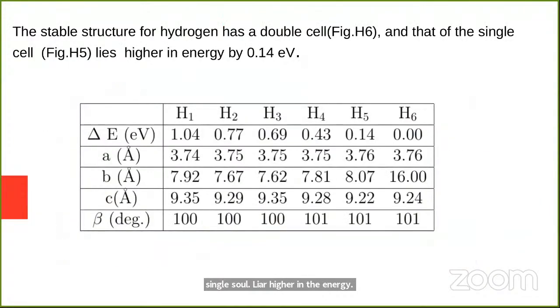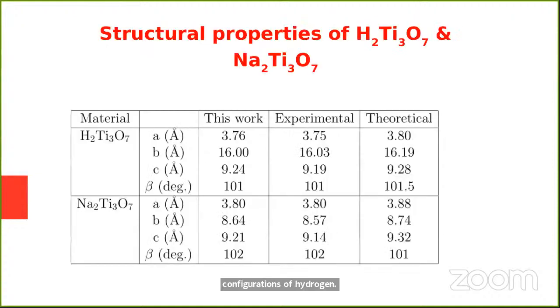And here in this table, we put all the lattice parameters for all the configurations. H1, H2 refer to all the configurations of hydrogen. And here we compare our crystal parameters for the two titanates with experimental work and other theoretical work. Our calculation confirmed that our data are less than the experimental data by less than 1% in all cases.